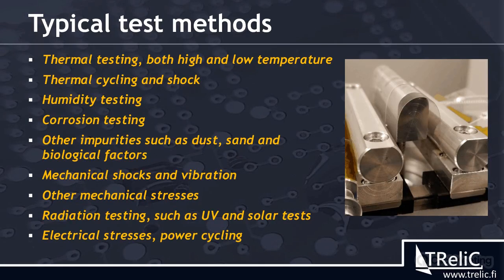However, what we quite often see is that thermal testing is not very efficient. So it can take a lot of time to get failures. And that's why we often use thermal cycling and shock tests, in which the temperature is cycled depending on the application from minus to plus 100, or depending, it can be very harsh or a lot milder. This is very efficient. Due to thermal expansion differences, it causes lots of mechanical stresses, and is, for example, in electronics, a very, very good test.